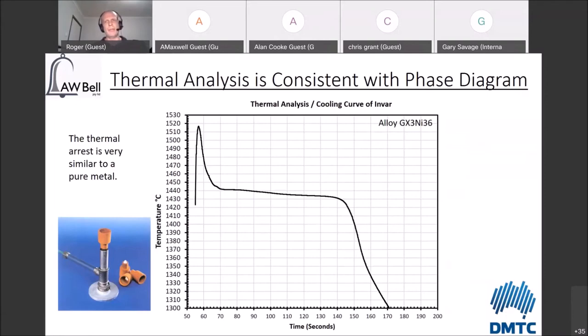So the thermal analysis is very consistent with the phase diagram. It tells us a lot about it. It does tell us that we are starting to kick off solidification around the 1440 to 1445 range. And it stays pretty constant through the thermal arrest until it finishes. Now, depending on how you interpret the tail end of a thermal analysis diagram, you could probably say that once it starts getting back to a linearity here is pretty much when you're finishing. So it's not completely flat because it doesn't have a very straight angle on this edge, but it's getting pretty close to behaving like a pure material.